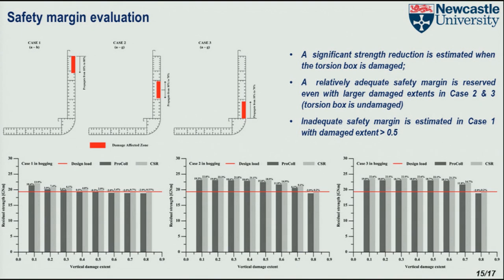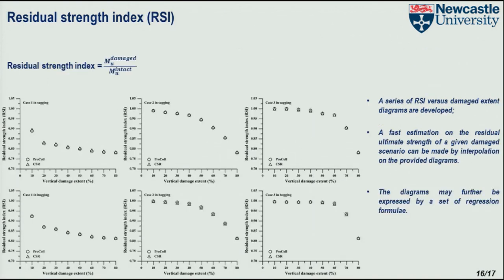Finally, the conclusions. In this study, we performed a parametric analysis to investigate the ultimate strength performance of damaged container ships using the simplified progressive collapse method, and also some validation by nonlinear finite element method. First, about the overall collapse behavior of the ship, we find that sufficient strength still remains in the container ship in sagging, even after it fails. And the collapse of an intact container ship in hogging experiences a gradual reduction of the post-collapse strength. However, the behavior becomes similar to the sagging collapse behavior if the ship is damaged.